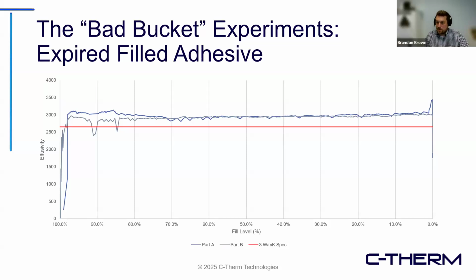The first thing I want to point out is that there's a red line on here indicating the 3 watts per meter Kelvin specification after it was converted to effusivity using the heat capacity and density information given on the technical data sheet. Given how poorly this barrel was handled, it was interesting to see that the formulation was stable beyond the first 15% of part B and maybe the first 3% of part A. Again, based on our experience, we'd expect the thermal performance to increase as the material cures. So this is the material as it's being transported through the pipe in an uncured state.